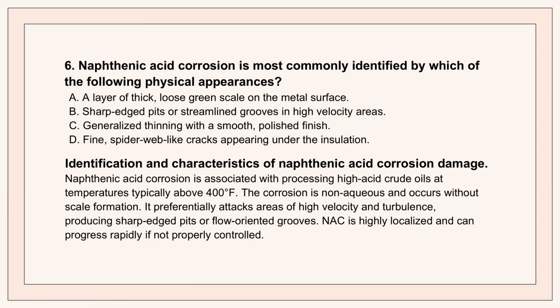Now, for a different kind of acid, naphthenic acid corrosion, or NAC. This is driven by organic acids in crude oil. For an inspector in the field, what's the telltale visual sign? Okay, so NAC happens when you're processing high-acid crude oils at high temperatures, and the damage is very distinct. It is most commonly identified by sharp-edged pits or streamlined grooves in high-velocity areas. The streamlined grooves, that's the key, right?